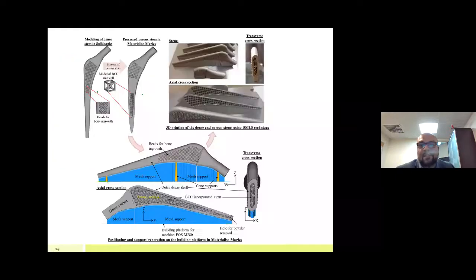So finally, we managed to design. We have a final design here, and we managed to print the stems, and we tested the stems in fatigue, and they achieved beyond 5 million cycles, which is what we are looking for. There is still room for improvement, but this is a good achievement for a concept stage. All this was done here in Qatar.